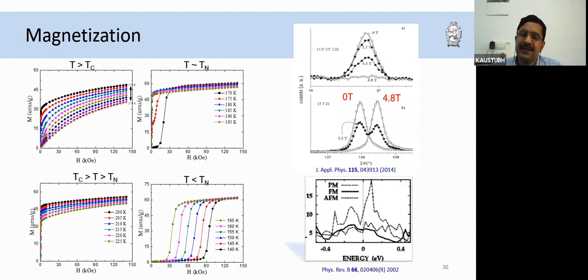And the reason for this, based on the DFT calculation, appears to be that the two states, the ferromagnetic and antiferromagnetic states, are very close in energy, so it should be possible. So although it stabilizes in the antiferromagnetic ground state, there is a very close ferromagnetic state to it in energy space.